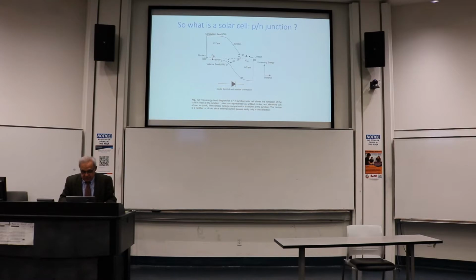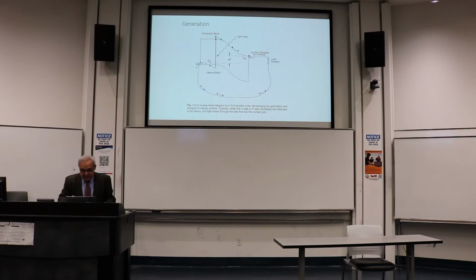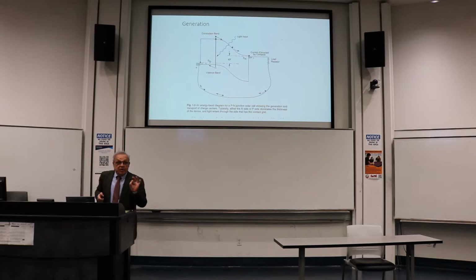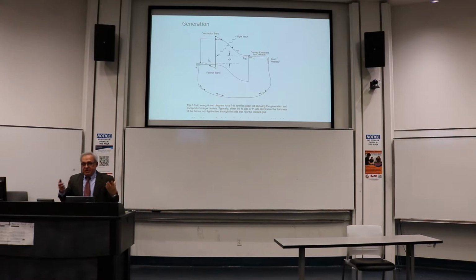Okay, maybe I will not show you this, but still, maybe this is important. This is the so-called energy diagram of the p-n junction. The light comes, takes the charge from one zone to another, then one charge goes down the slope, these bubbles go up, and you separate the charges, and this is the voltage. You need a p-n junction. To make a p-n junction, you put silicon in the hot furnace, and you heat it. And you have dangerous gases that should be there. So this is big technology.